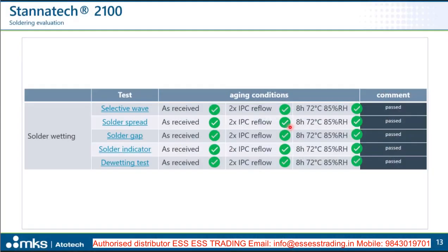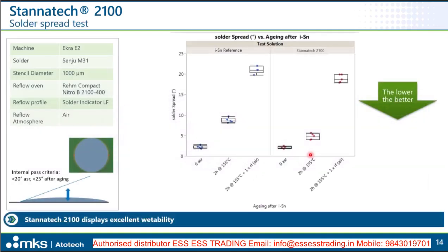Let's go to the soldering performance. What we usually do when we check our processes is different kinds of soldering tests to check the solder wettability of the immersion tin layer. On one hand, there are solder tests where solder paste is printed and then the solder spread capability is measured, or tests like solder float tests, where liquid solder is applied to the final finish and the wetting is measured. These tests were all done with different aging conditions: as received, after IPC reflow and after thermal and humid aging. Let me go to some of the tests, starting with the solder spread test.